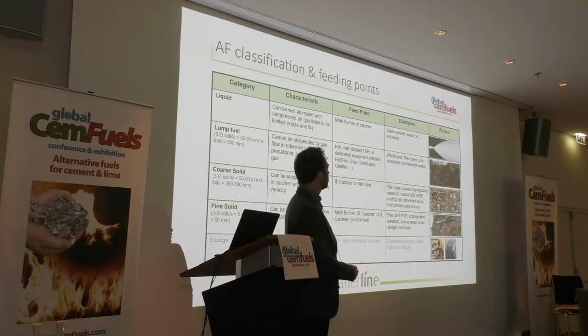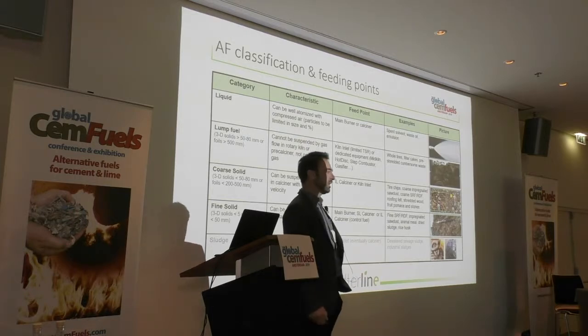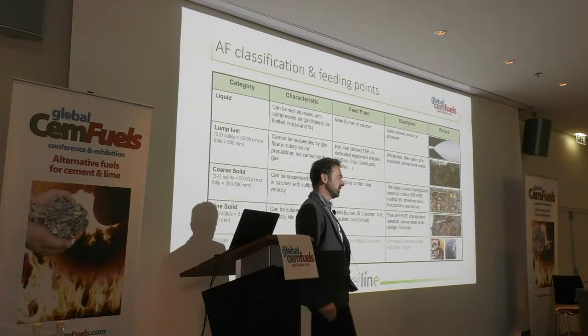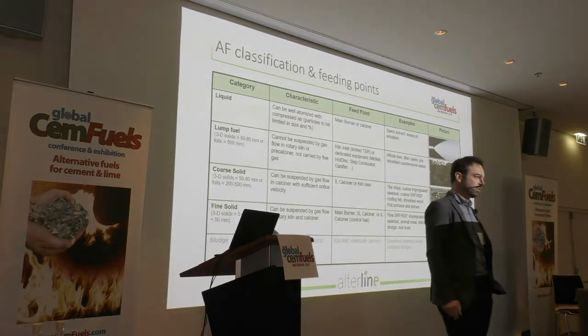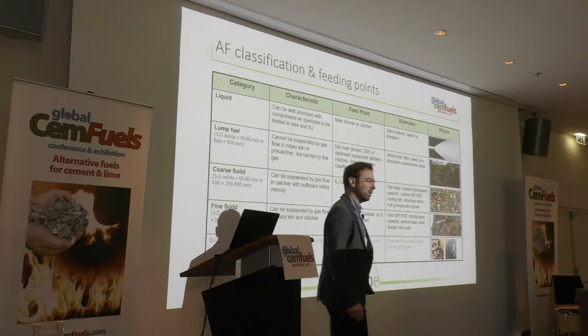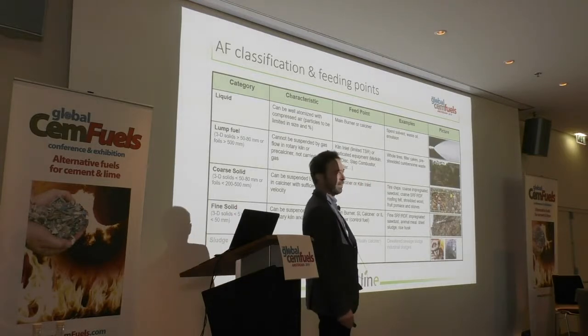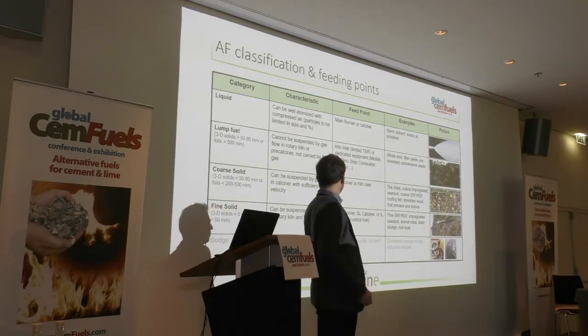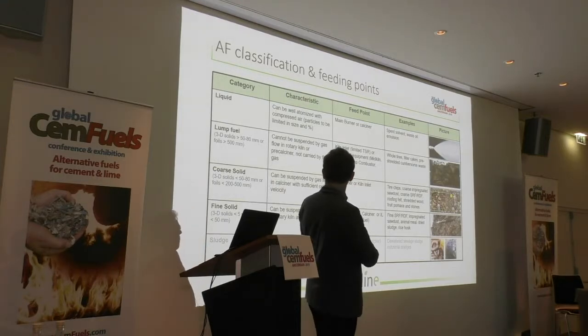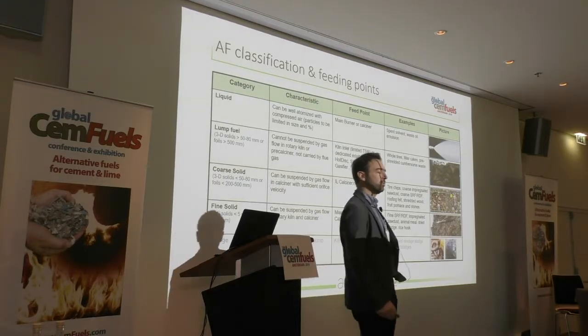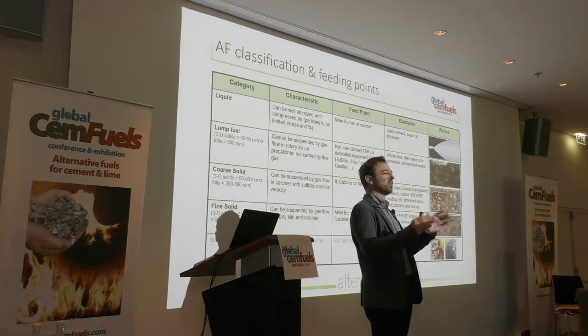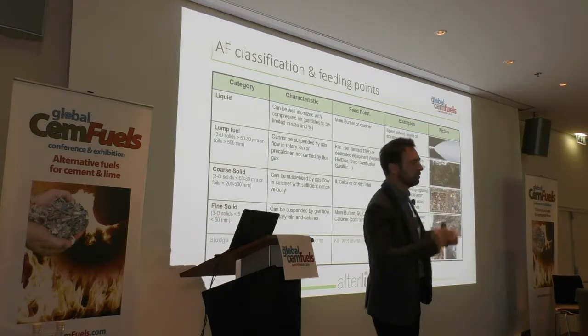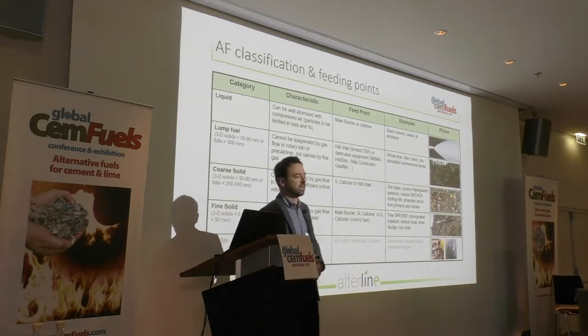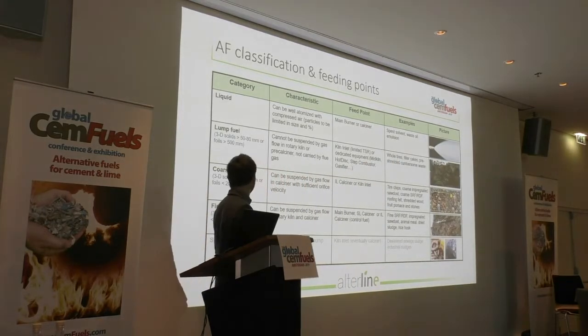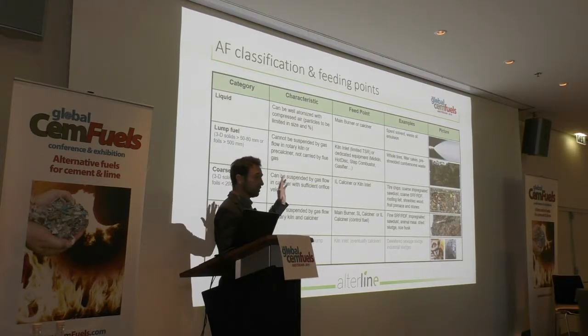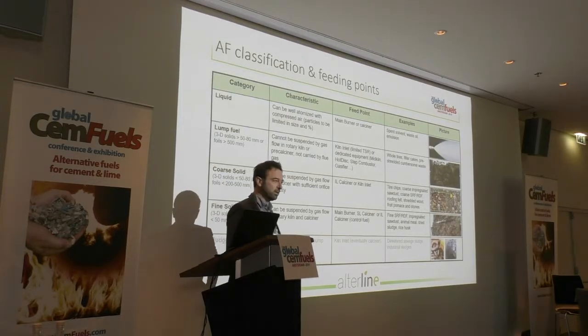It's like whole tires, filter cakes. You will see it during the visit on Friday for the one doing the visit in Lix. They have some filter cakes at the kiln inlet. If I'm not wrong, they move it from the calciner to the kiln inlet. Coarse solid, I mean solid with three-dimensional particles, 50 millimeters up to 100 millimeters, depending on the orifice speed and the calciner design, and 2D material, 200 millimeter sheet, can be higher depending on the handling equipment.